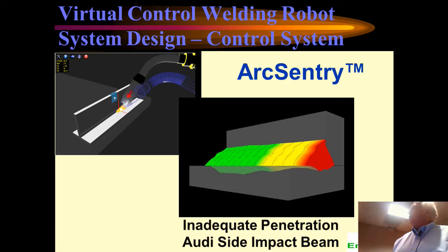This particular one was a weld on, we've got a system installed on a line over in Norway that's making the side impact beam that goes underneath the dashboard of a car to protect it from caving in when it gets a side impact on an Audi. And in this particular case, there was a fingerprint on that aluminum part, and you can see they got a lack of penetration defect because of the arc instability that occurred because of the oil in that fingerprint. So we can detect those kinds of things with this system in real time, and then we can produce an afterward digital quality control report that allows you to bring up any of these graphs and look at the weld from one end to the other.